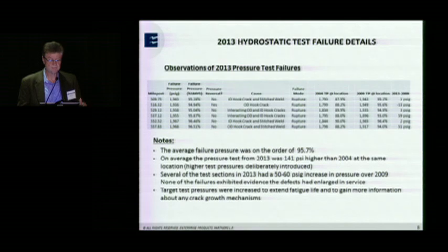And this is just the summary, once again, of the milepost and the failure pressures, and you can see the range is basically 95% SMYS and up. And they were all ruptures. In one case, on the far right-hand side, you saw the pressure reversal at minus 13 PSI. In a couple other cases it was higher, 59 PSI higher than the previous hydrostatic test. We readjusted some of the test sections so we could test a little bit higher, so that one failing at 59 PSI higher just happens to be that we tested it higher.